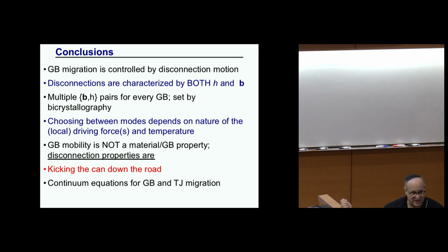That doesn't work there because in that movie, they take the sample, they anneal it until nothing's moving anymore. Then they apply stress and it starts to move those disconnections. So it's the stress coupling term that's driving it, not the curvature. But yeah, this version works.